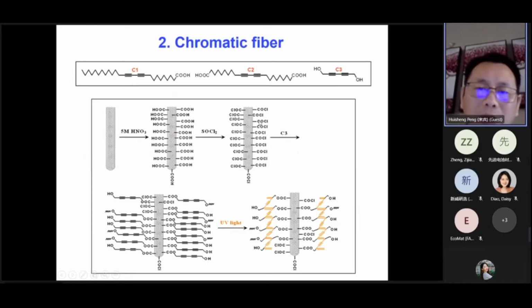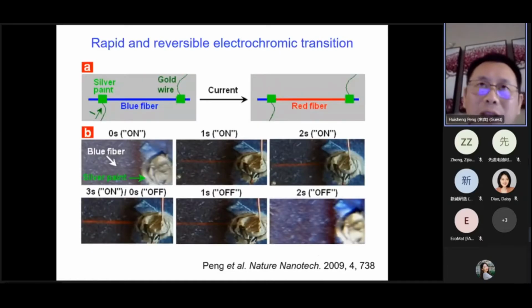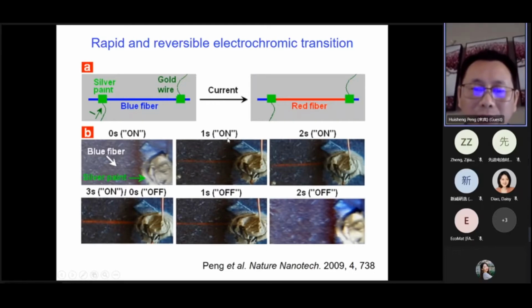Then we also try to incorporate these functional polymers, and we are more focused on these chromatic polymers. Here I just give you an example. These are diacetylene molecules, and they can be connected to the carbon nanotubes with very simple reactions, and then under UV light they can go through chemical polymerization to produce polydiacetylene, and form the composite fibers. Very interestingly, the as-prepared composite fiber is blue. When we pass an electric current, it quickly changes the color to red. The color change is totally reversible and very quick, in less than 1 second. And this is the first example.